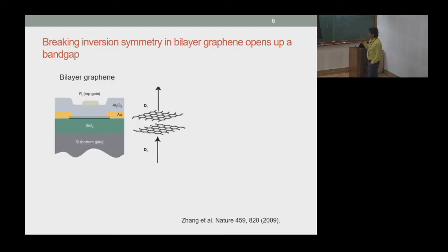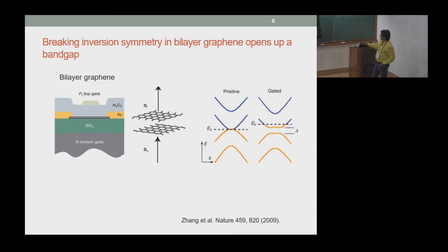So one practical world example of the symmetry breaking is if you have one layer of graphene, so you have one pair of Dirac cones, and you put another one, you have another pair. But as you turn on the hybridization, the bands are no longer linearly dispersing or Dirac-like. They have a quadratic nature. Okay, and in the absence of a perpendicular breaking of symmetry, in this case by electric field, you have a gapless system. At Fermi energy, the excitations are gapless, much like graphene.